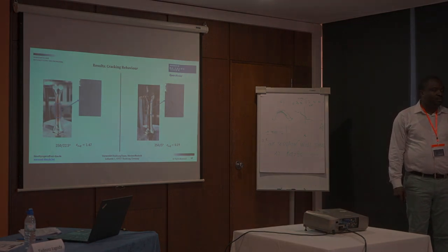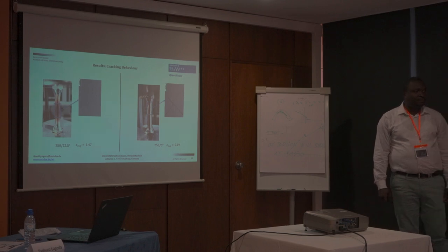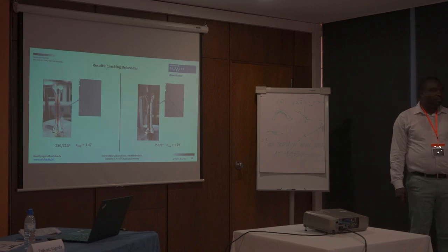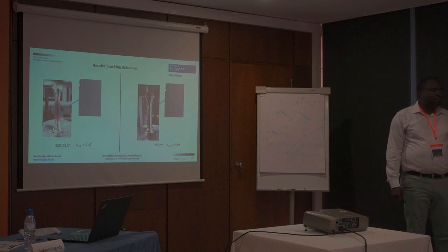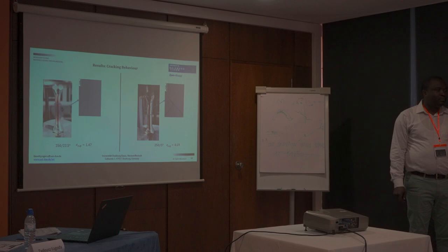So when you have the high torsional angle, then you see in your gamma that the grains are full of dislocations, right? So there's a lot of dissipation by the dislocations occurring at that moment. Now, what you're saying is that due to this temperature you could get some self-annealing, so some of the dislocations could run out, so the real effect could be even more dislocations than you think. But that's a more complicated mechanism, but the basic mechanism of the heat up is